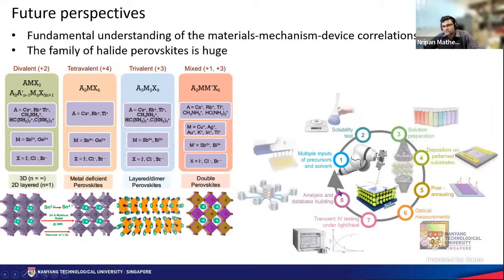Which is why we are also planning to do self-driven synthesis of these material systems, where, let's say, we would have a robotic system, because it's a solution processable material system. It's pretty straightforward to make a different composition. So utilizing different precursors, we can do automated solution preparation, deposition, and then measurements. We will not be able to measure directly the ionic properties, for example, but we'll have to measure something that is a proxy for ionic transport. So, how quickly does the electronic transport change for 10 pulses, 15 pulses, which is an indication of how mobile the ions are within the system, etc. This is something that we would be exploring as well.